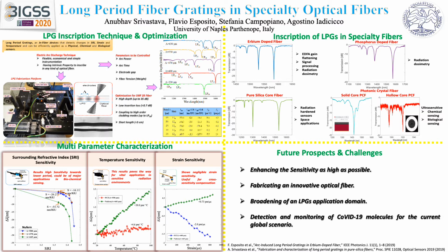There are several inherent effects that arise during the arc discharge mechanism while inscribing the grating, namely dopant diffusion, stress relaxation, geometrical deformations, and changes in glass structure. The predominant effect prevailing in the arc discharge mechanism depends on the writing condition and the type of optical fiber we use. So the most appealing feature of the electrical arc discharge technique lies in its intrinsic property to inscribe gratings in all kinds of optical fiber.